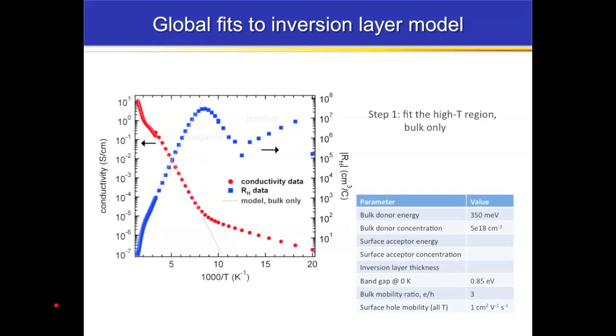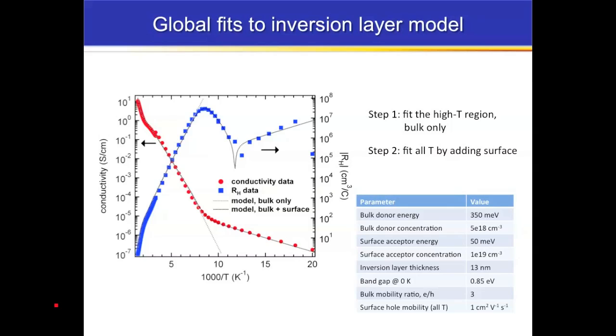So I show here our fit for the data that I've been showing. If we just use a bulk feature with just a bulk donor, we can't fit the low temperature data at all. All we get is monotonic changes, as you would expect. You can barely see it, but the fit is this dotted gray line. If we also invoke the surface acceptor idea, this surface inversion layer, we can fit the data quite well, especially for the Hall coefficient. In this particular case, the model gives us a certain concentration and ionization energy for the bulk donor, and the surface acceptor is at higher concentration at about 50 meV ionization energy. So we believe, based on this data as well as some other things we've been doing, that we very likely have a surface inversion layer in pyrite, and that's probably responsible for most of the problems that pyrite has seen in terms of its voltage output.